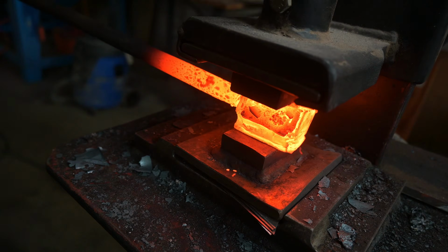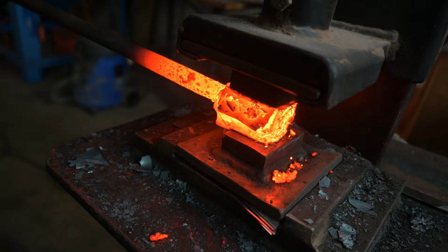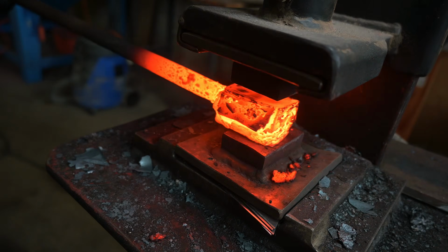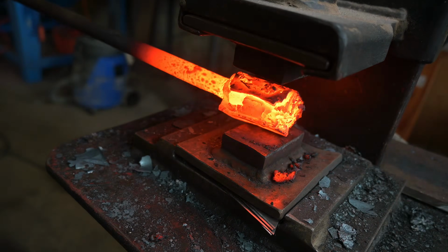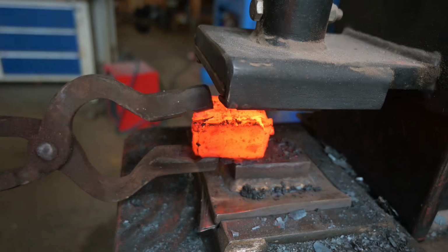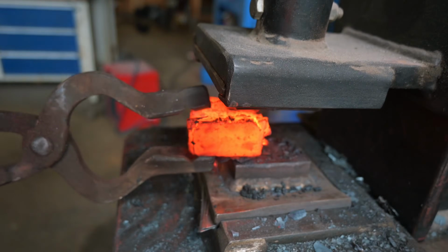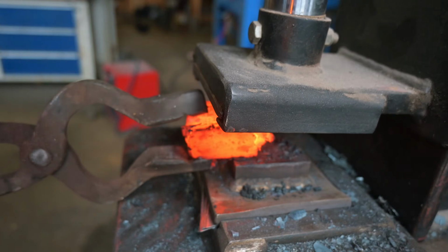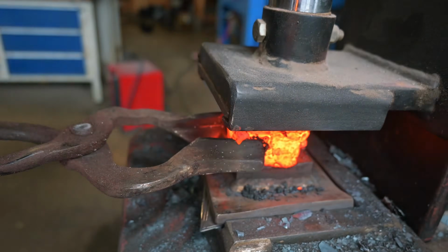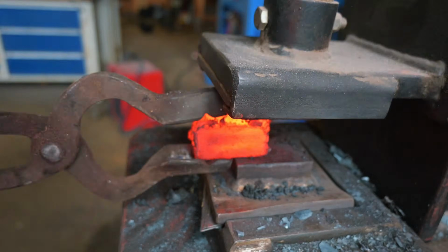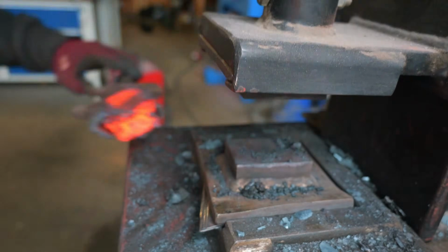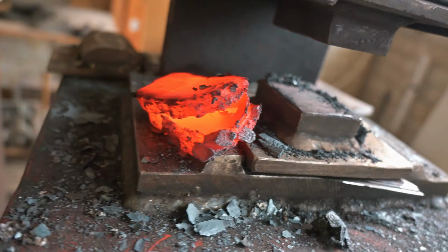Then I proceeded to use a lot of flux to get the billet welded solid again. I welded a handle on the block of steel, but it broke off after the first heat and the steel was super crumbly and it wasn't really welding. And then it split completely on me right down the middle.